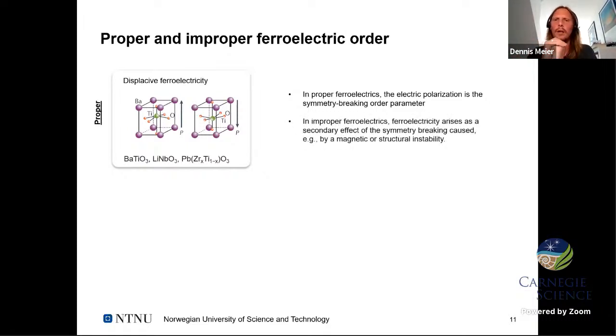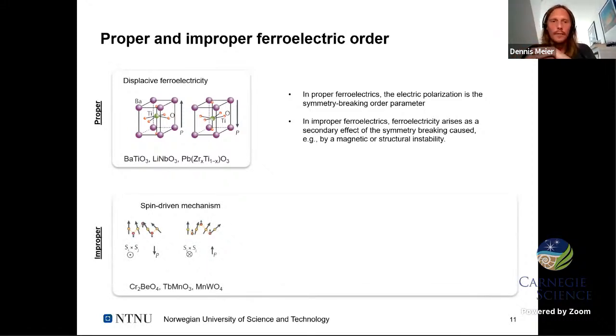In contrast, when I'm talking about an improper ferroelectric, the ferroelectricity arises only as a secondary effect due to the symmetry breaking, which is caused by a magnetic or structural order. So this is different. Here, the ferroelectricity is not the symmetry breaking order parameter. It's only coming because of the coupling to the symmetry breaking order parameter. And over the last years, different examples have been established, especially because of the intensive research on multiferroics. That's where people really discovered a lot of materials with unusual ferroelectric properties, and it was kind of a revival of improper ferroelectricity. One mechanism is a spin-driven mechanism that can drive an electric polarization. We will get back to that in a minute.